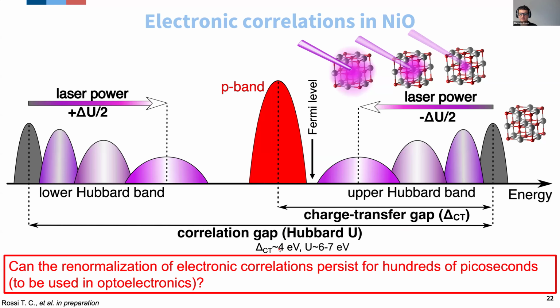It's typically of the order of 4 electron volts in nickel oxide. And now the consequence of what we call the electronic correlation, so the repulsion that takes place between electrons when they have opposite spin in the same 3D orbital, is to split the 3D density of states into 2 bands. The 2 bands that are highlighted here in gray.